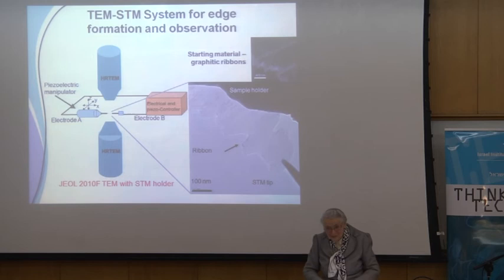This is a laboratory, so we can do the following thing. When you have a very low voltage, you don't get very much heat, but when you increase the voltage, it goes up linearly, and then it just takes off like crazy. And at this point, the carbon atoms start moving along, finding different positions, and they go from this disordered thing here, lights are on, so it's a little hard for you to see, to something that's very ordered.